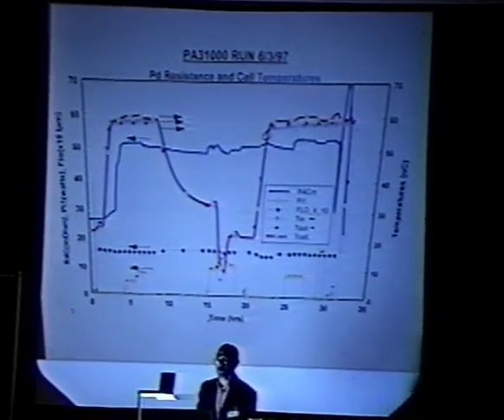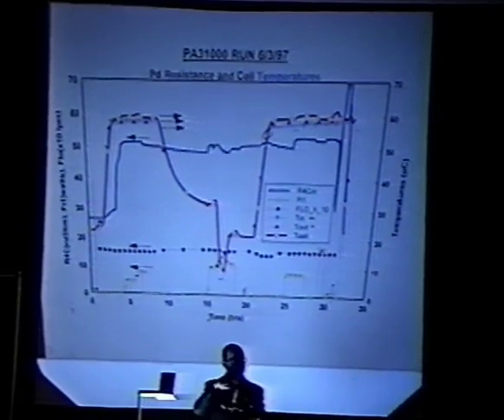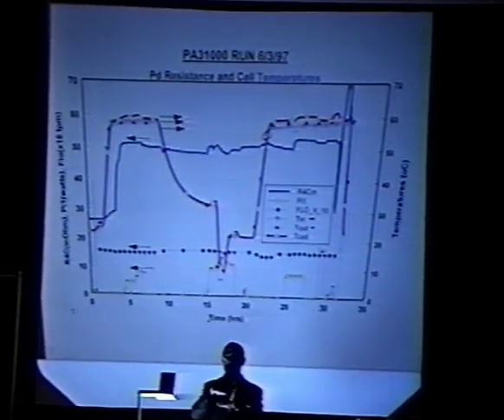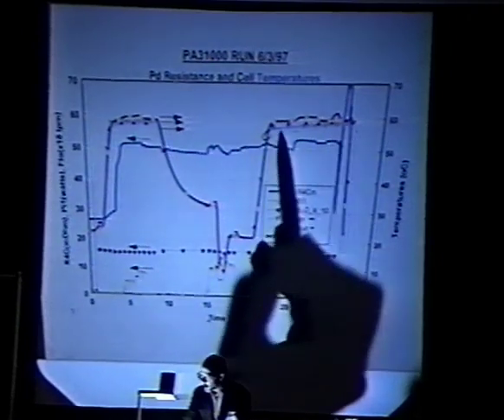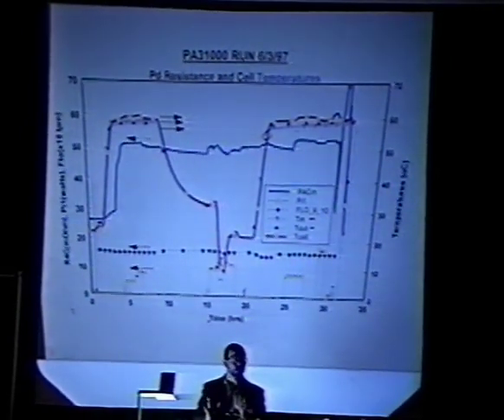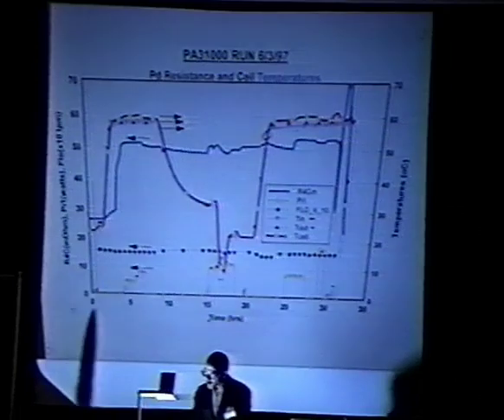And with most calorimeters, you really don't believe the data until you get to a steady state situation. Then the delta T makes some sense. And it's the same thing here. But what you see is there's a very long period of time right through here where the outlet exceeds the inlet, in this case at most by 2 degrees centigrade, which is not a whole lot compared to some of the runs I've seen. But let's go back and just take a look.